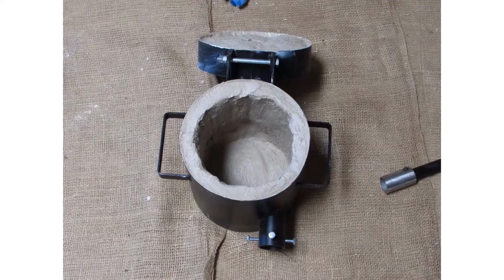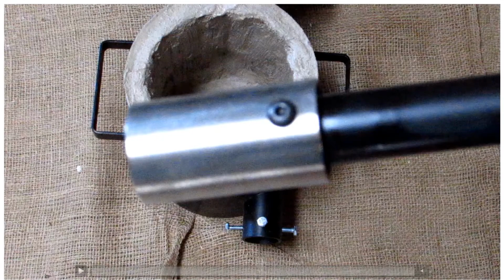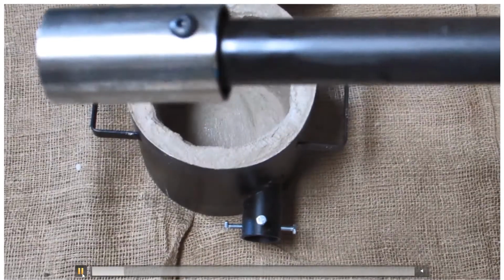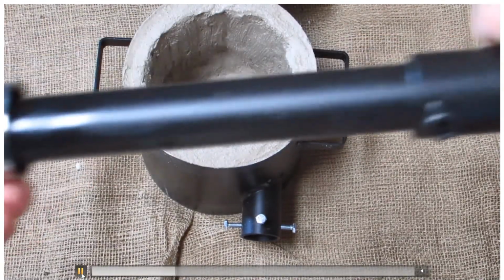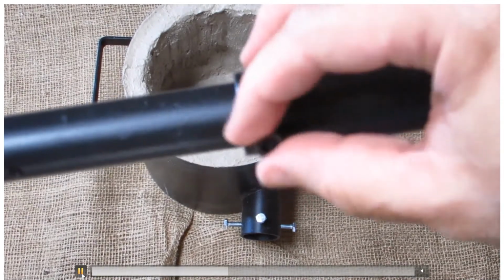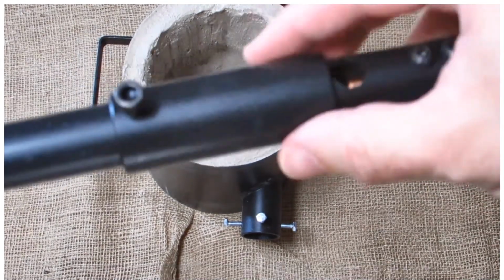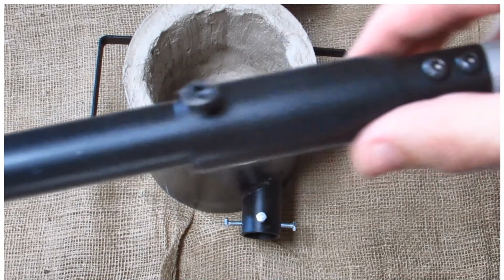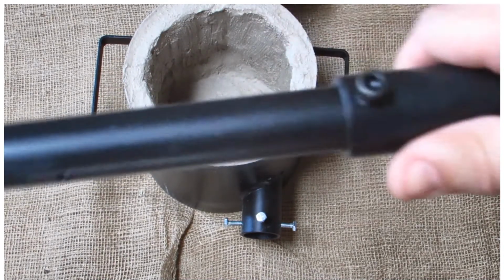Since I rigidized the ceramic wool, I had more confidence that the mortar wasn't going to flake off upon use, and it was a little bit more resistant to impacts, like if I hit the crucible on the side of the furnace or something like that. One thing that this furnace has that I really like is a really good burner, and you can adjust the intake by moving the cylinder over these small holes. So you have 3 holes, so you can adjust the amount of air going in.